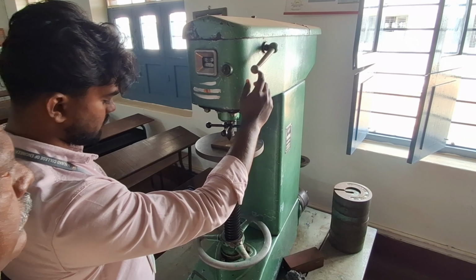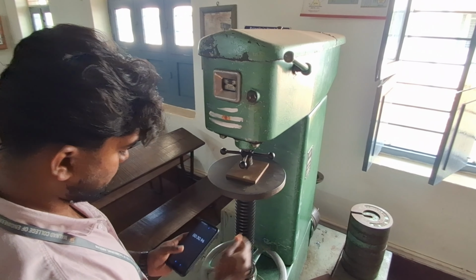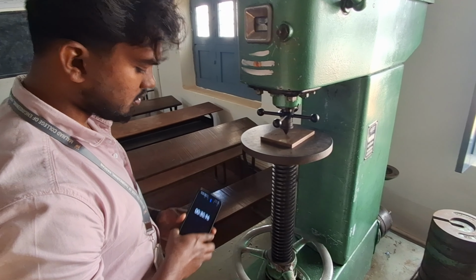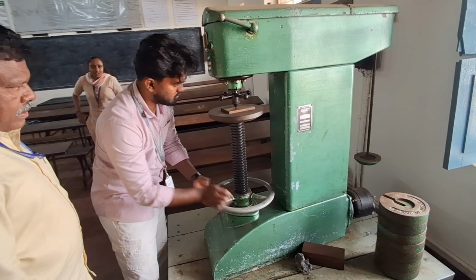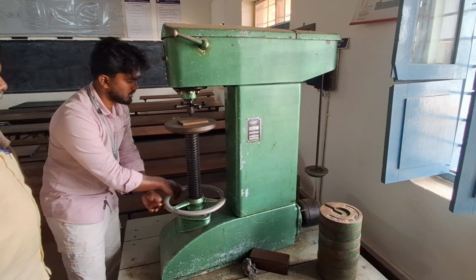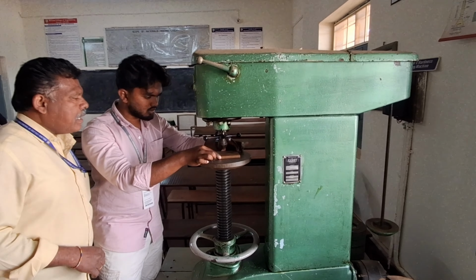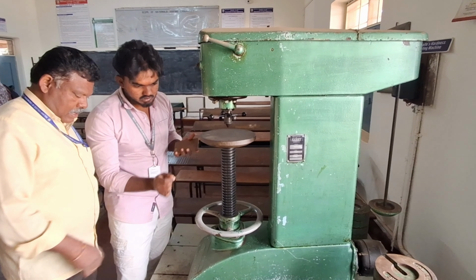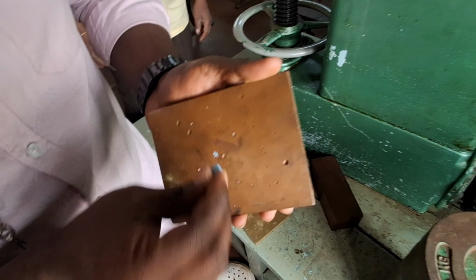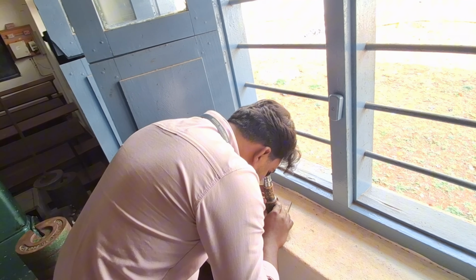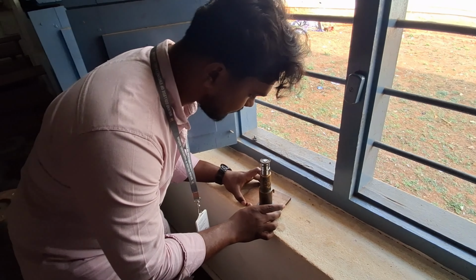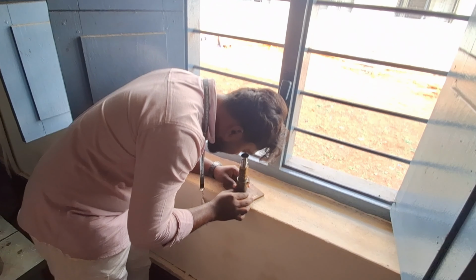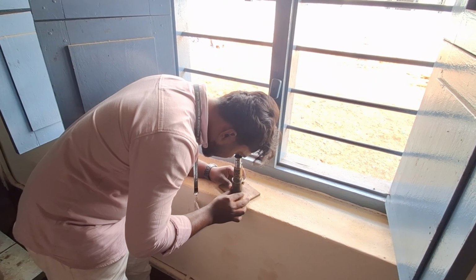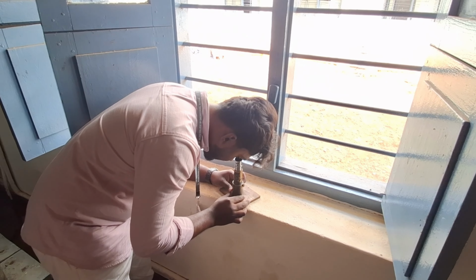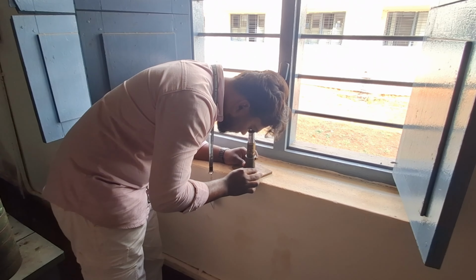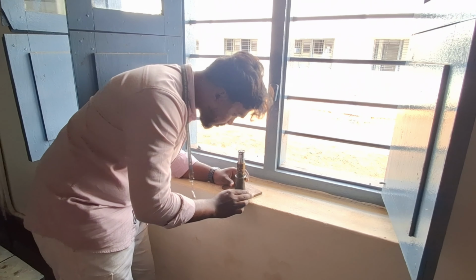Once the required load is reached, it is maintained for about 30 seconds as per the laboratory testing conditions. After the specified time, the load is released slowly by rotating the hand wheel in the opposite direction. The specimen is then removed carefully from the machine. An impression formed on the surface of non-ferrous specimen can be clearly observed. The diameter of the impression is measured using the Brinell's microscope. The diameter is measured in two perpendicular directions and the mean value is calculated. The observed readings are noted in the tabular column. Using these readings, the Brinell hardness number of the given non-ferrous material is calculated.